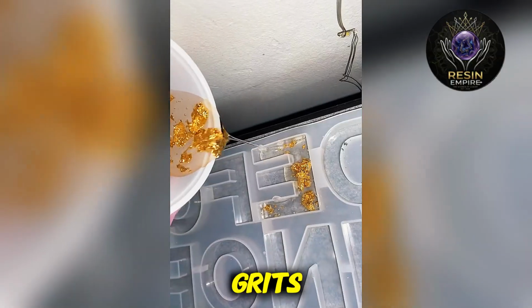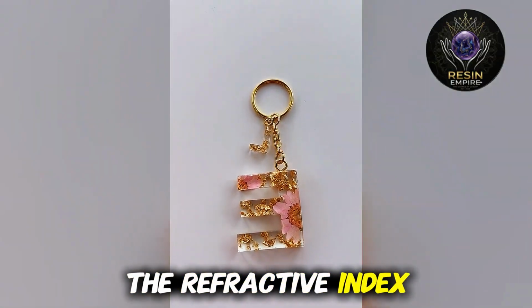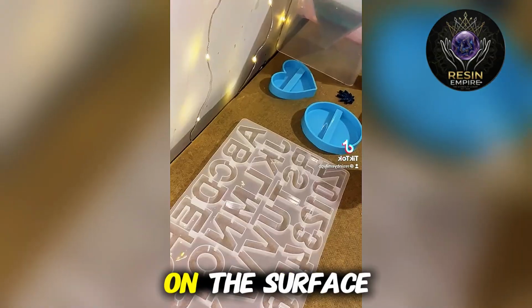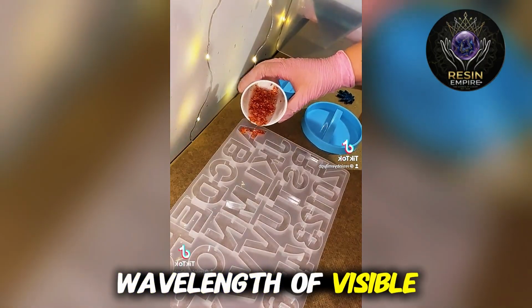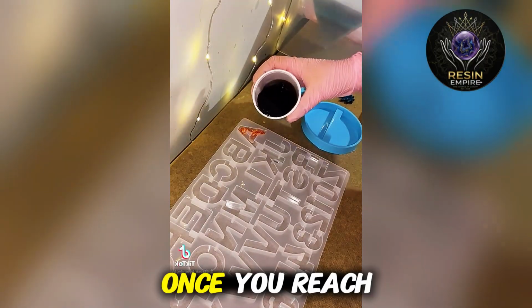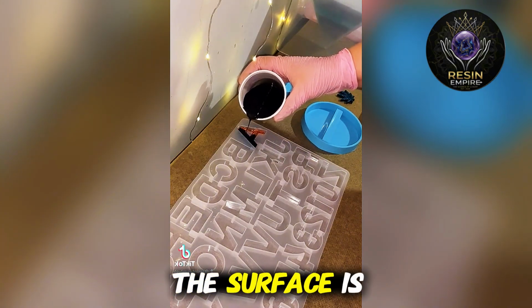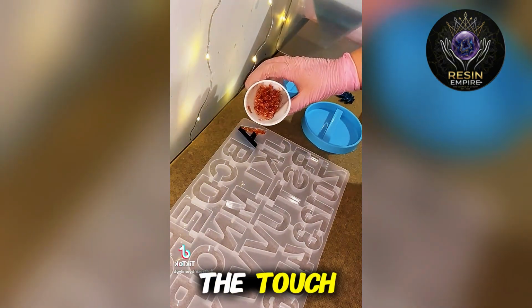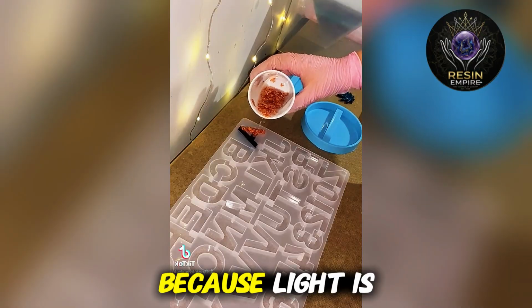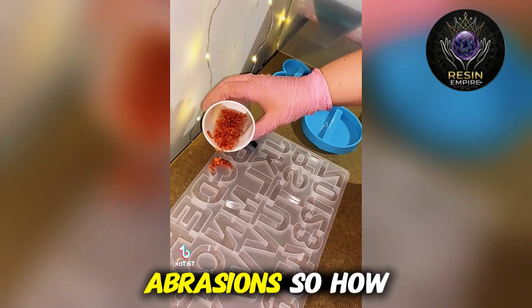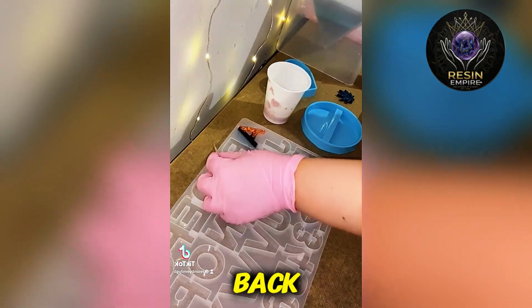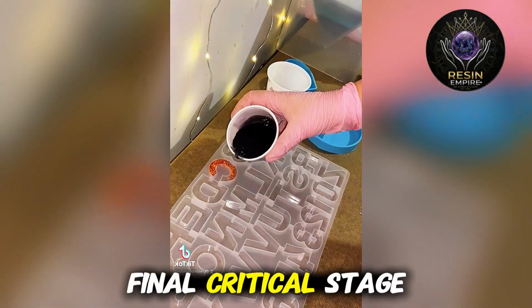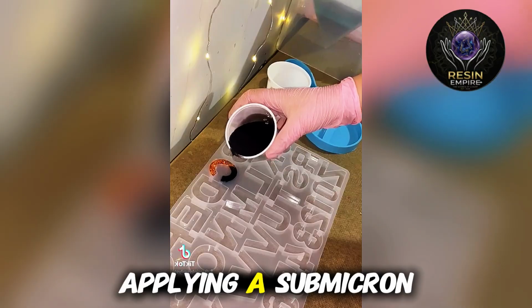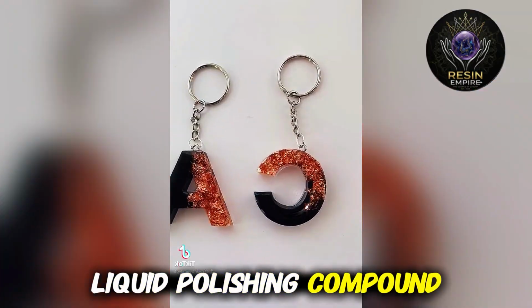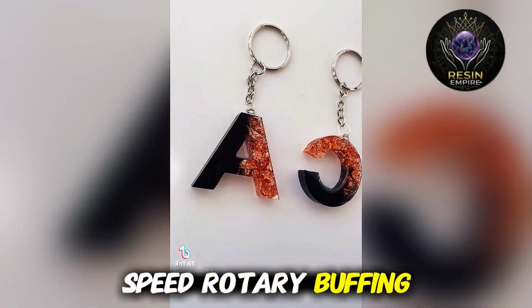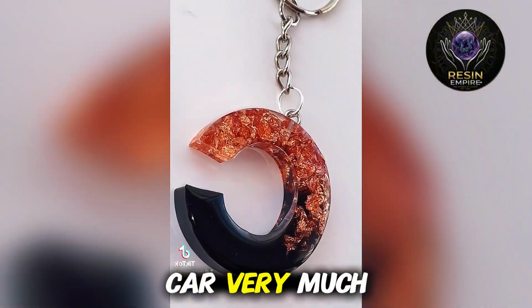As you move up in grits, you are changing the refractive index. You are making the microscopic peaks and valleys on the surface smaller than the wavelength of visible light. Precisely. Once you reach 3000 grit, the surface is flawlessly smooth to the touch, but still slightly hazy to the eye because light is still scattering off microscopic abrasions. So how do you get the clear window back? This brings the artist to the final critical stage. Applying a sub-micron liquid polishing compound with a high-speed rotary buffing wheel. Like polishing a car. Very much so.